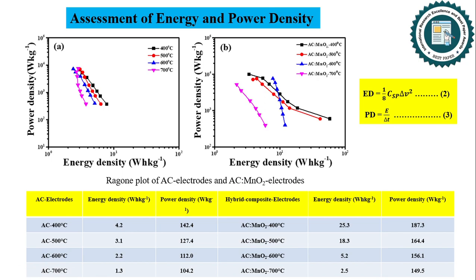watt-hour per kg at power density of 142.4 watt per kg, followed by AC 500 degrees centigrade having energy density of 3.1 watt-hour per kg at 127.4 watt per kg power density.